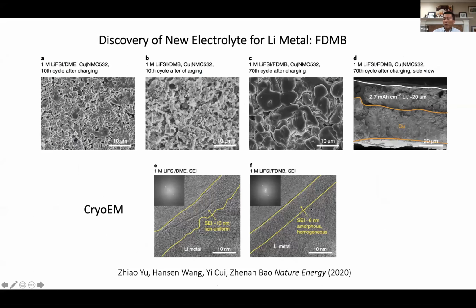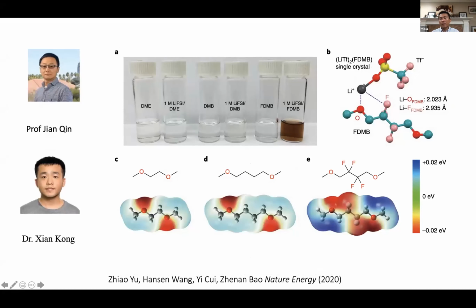So then we go deeper into that, using cryo-EM, which I'm going to mention in a minute. And we find out the SEI layer is a lot more uniform. It's amorphous, it's a very thin SEI. In the lithium metal deposition, the grain size is bigger. The coordination solvation shell of this lithium salt with this FDMB is very special. You notice right here, this is FDMB with lithium salt in there. This has color. The usual lithium battery electrolyte has no color.